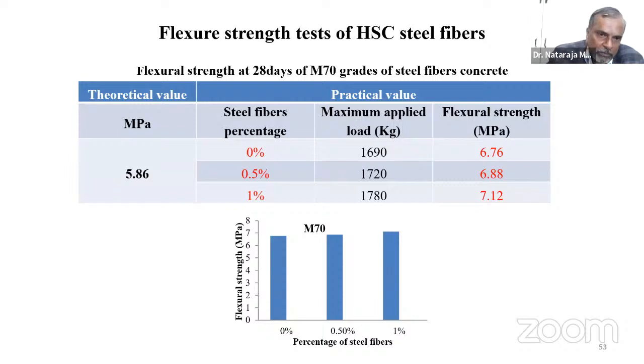And as the steel fiber increases, kindly see that the strength of the concrete also increases, the flexural strength. Today, the pavement concrete is to be designed for the characteristic flexural strength. It is not the characteristic compressive strength. That also we have done in our work. Depending on the range of the flexural strength, we can do the mix design. So with 0.5% of fiber and 1% of fiber, the flexural strength is increasing. But mind you, if your idea is only to increase the flexural strength, don't add fibers. We need to decrease the water cement ratio and get the increased flexural strength.